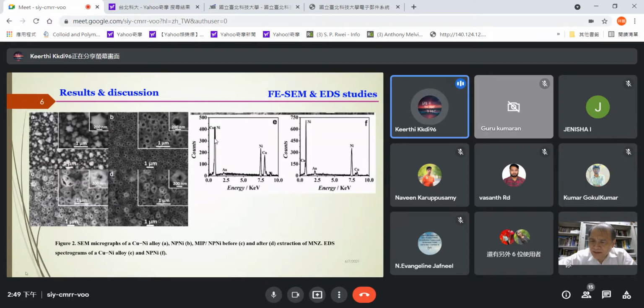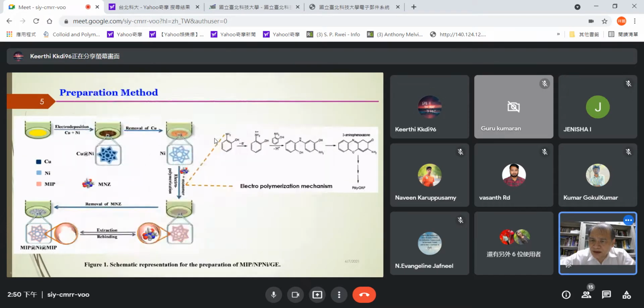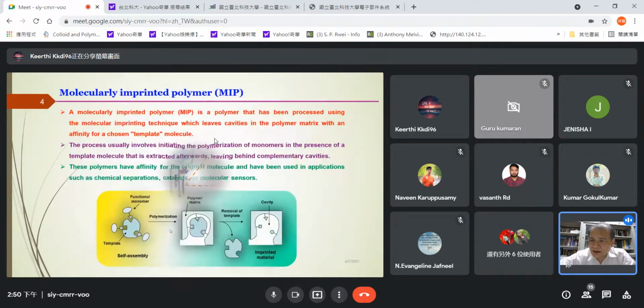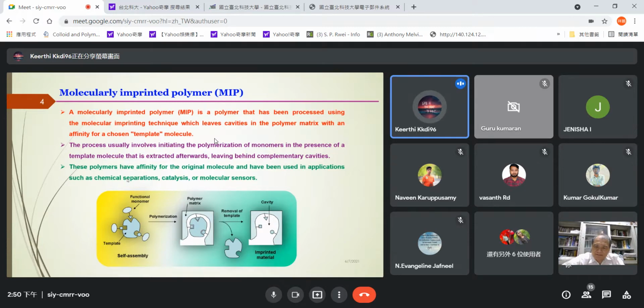No, Professor. The author did not mention this in the article. Yeah, back to your previous slide. The molecular imprint basically is a molecular size, right? So you remove the template, but it looks to me the cavity is larger than the molecular size. Is that normal, or why? Can you explain that? No, Professor. The cavity should be at the molecular level. But the author reports that selectivity comes from the molecularly imprinted polymer and sensitivity enhancement from the nanoporous nickel.